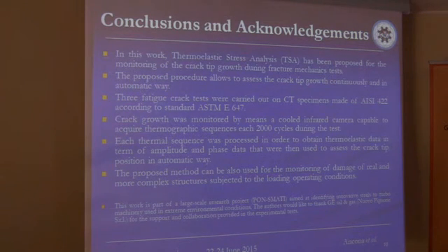The crack growth was monitored by means of a cooled infrared camera capable of acquiring thermographic sequences every 2000 cycles. Each thermal sequence was processed in order to obtain thermoelastic data in terms of amplitude and phase signal, so as to assess the crack tip position in an automatic way.